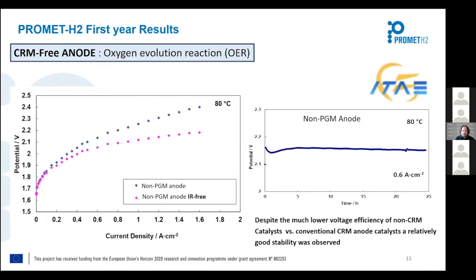As you can see in the left graph, we have a polarization curve of this kind of material. It means this polarization curve represents a MEA that was loaded with non-platinum group metal at the anode side. As you see, the performance is not so high, but quite promising in terms of stability. I think this is the starting point, and more investigations need to be done, but it's a good starting point.